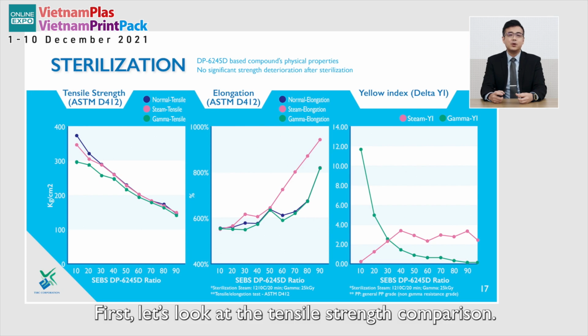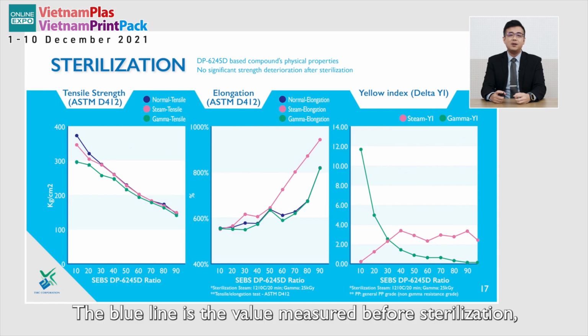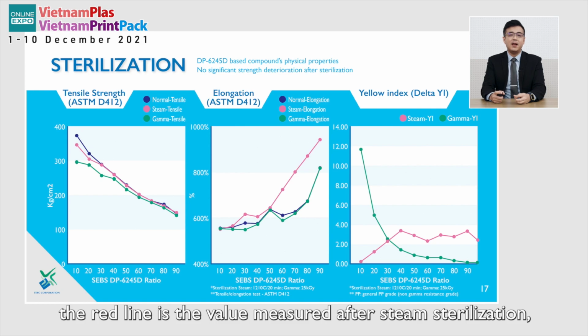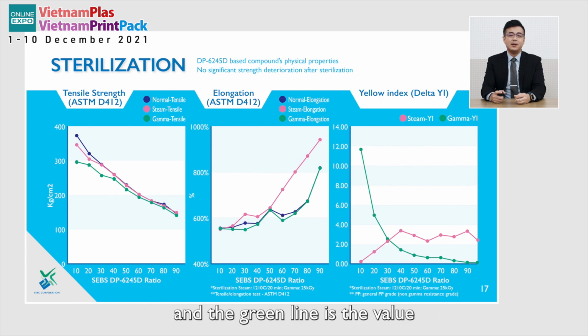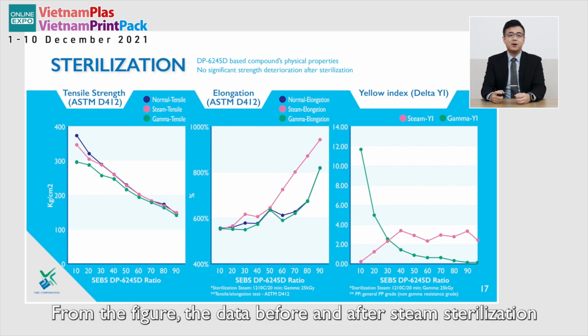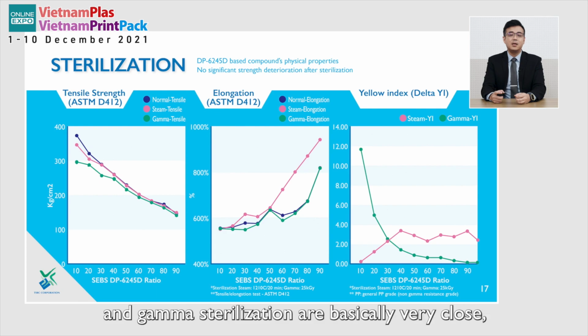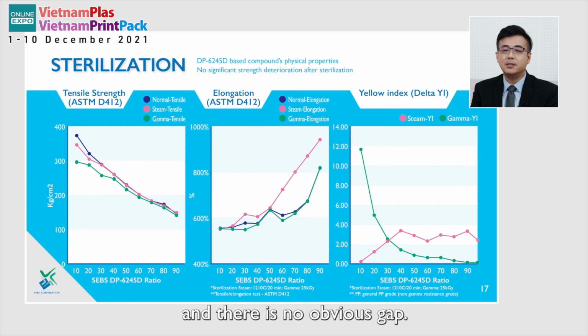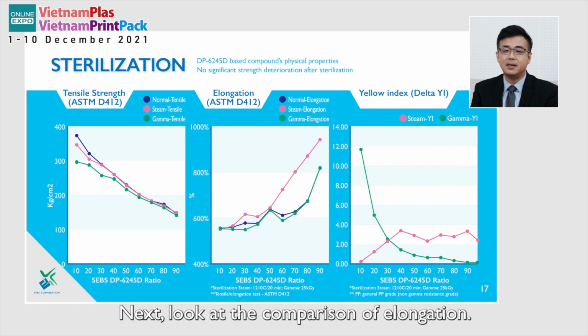First, let's look at the tensile strength comparison. The blue line is a value measured before sterilization, the red line is a value measured after steam sterilization, and the green line is a value measured after gamma sterilization. From the figure, the data before and after steam sterilization and gamma sterilization are basically very close, and there is no obvious gap. Next, look at the comparison of elongation.